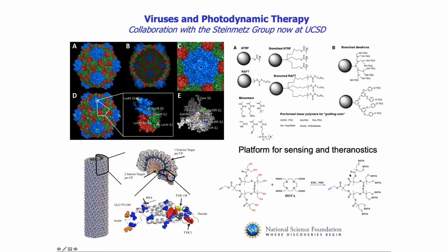And then finally, showing to you the extension of our work, we used actually plant viruses. Now, these are not coronaviruses. They look like them, but they're really plant viruses based on the cowpea mosaic virus analog. We can functionalize them with dendrons, as I showed earlier, or do grafting of polymer brushes. And in fact, we have utilized this to template the adsorption or grafting of DOTA and chelation of platinum ions, which can perhaps be used for photodynamic anti-cancer therapy.